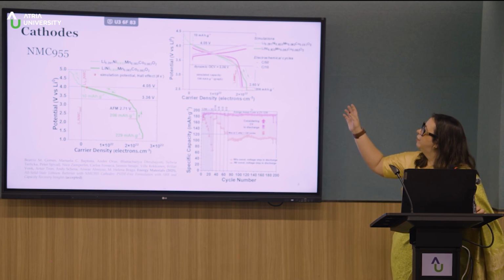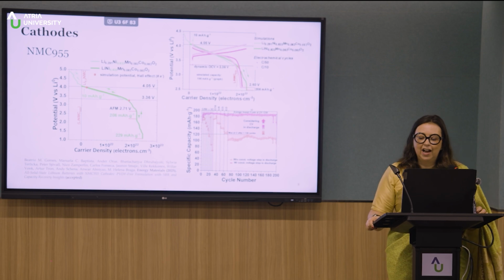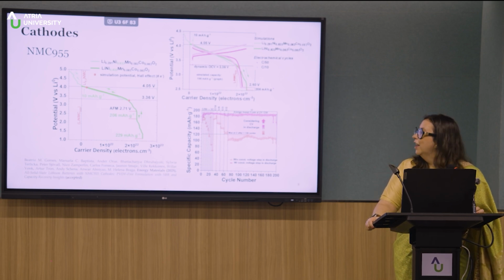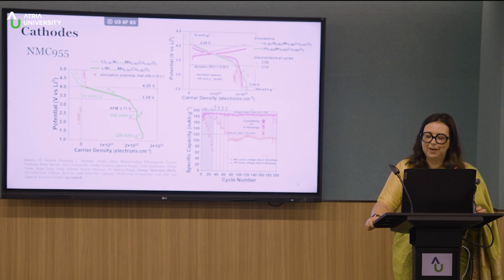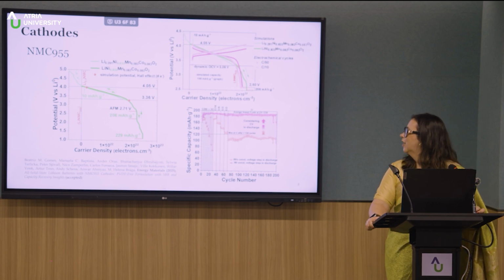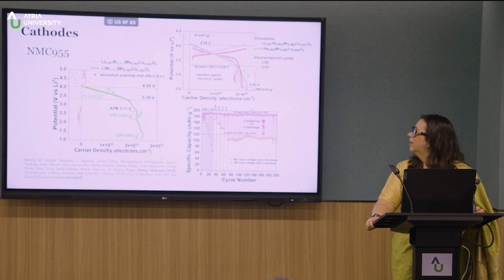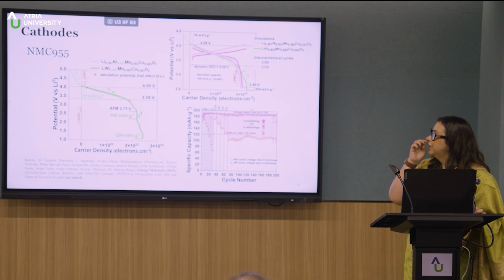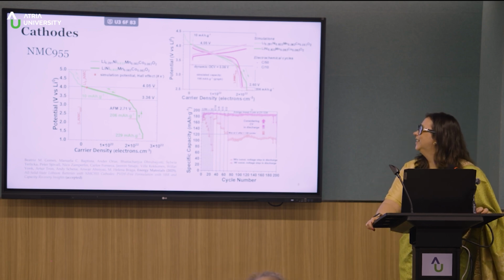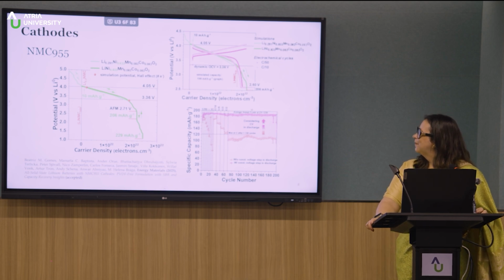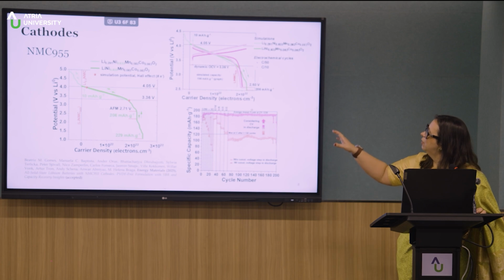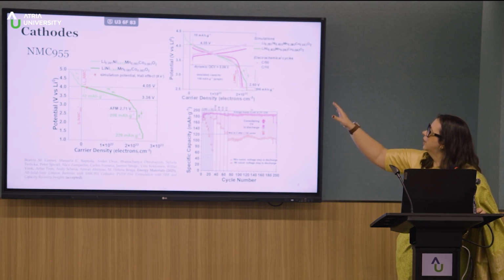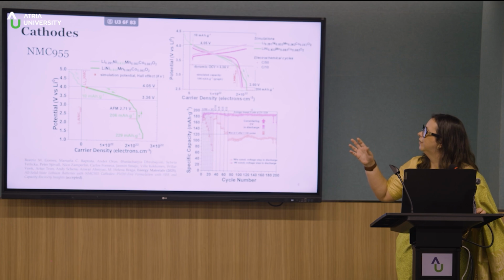How do we avoid also PVDF? PVDF is a very good binder, but in the European Union it is being banned because it contains fluorine. So we were substituting PVDF by a binder that is SBR, which is not the final solution, but at least it doesn't contain fluorine. And so what we did was that we started to understand how the discharge curve and the charge curve would behave.